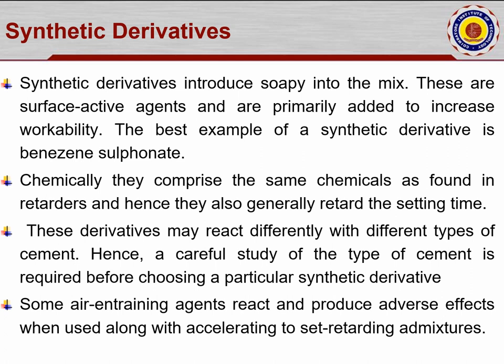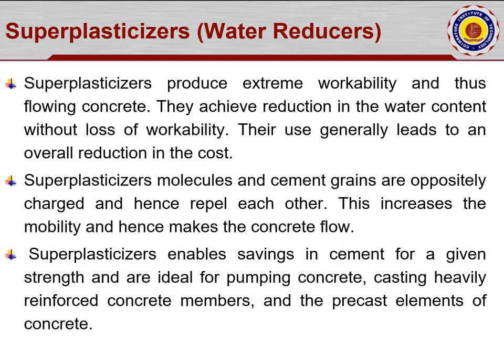Synthetic derivatives introduce air into the mix; these are surface-active agents primarily added to increase workability. The best example is benzene sulfonate, which is a salt-based content. Chemically they comprise the same chemicals found in retarders, and hence they also generally retard the setting time. These derivatives may react differently with different types of cement — careful study is needed to identify how much quantity can be adapted to a particular concrete. Some air entraining agents may also react and produce adverse effects when used with set-retarding admixtures.